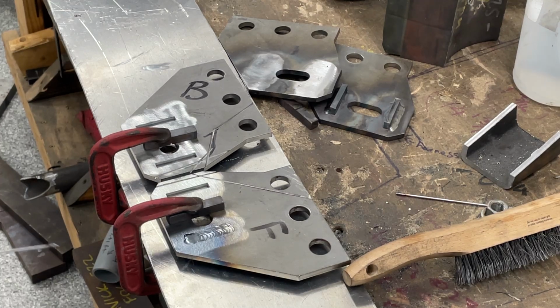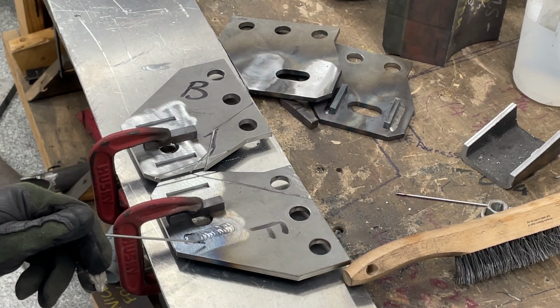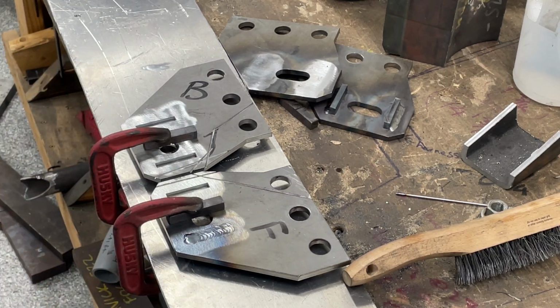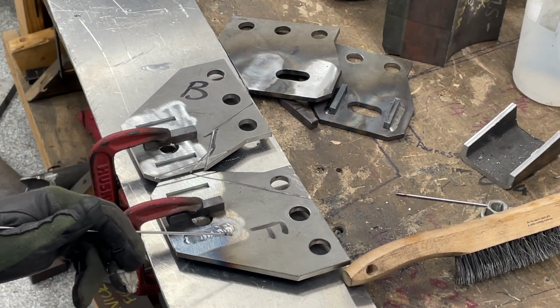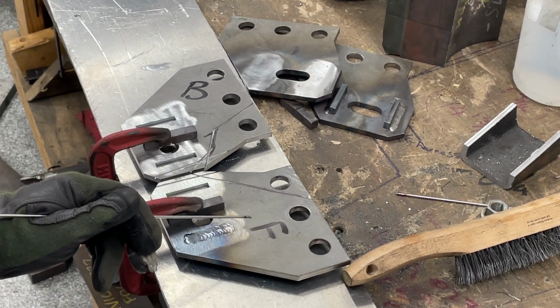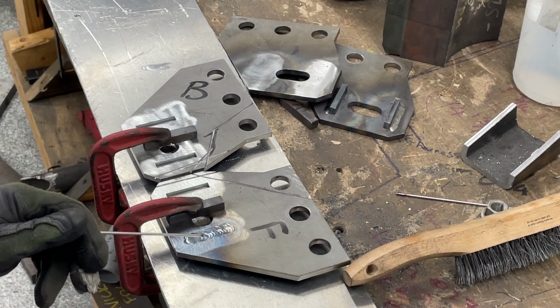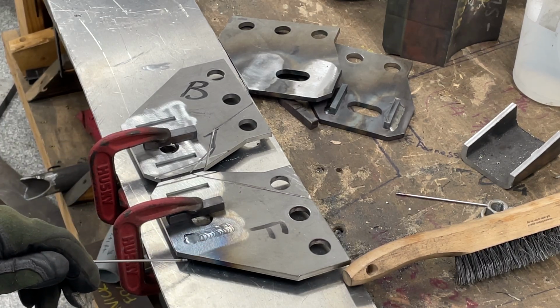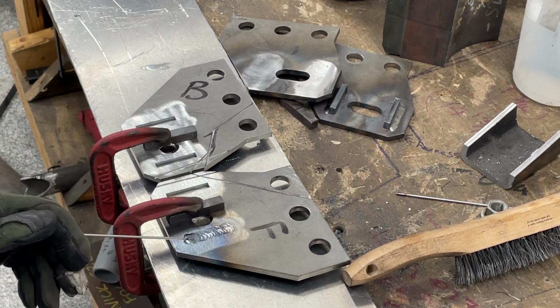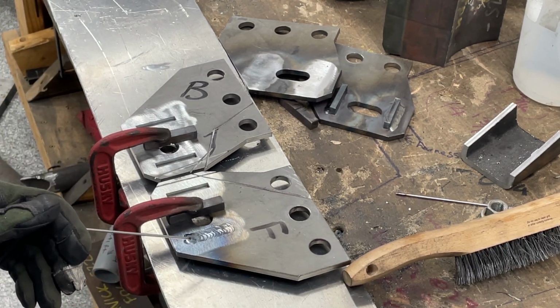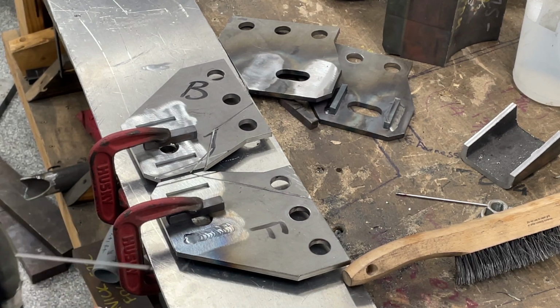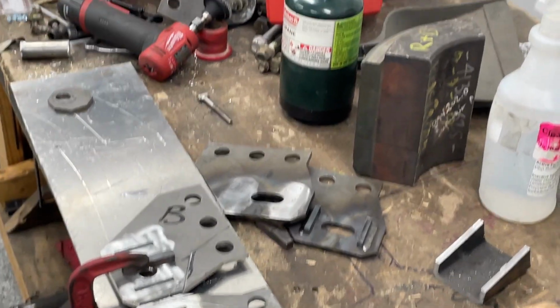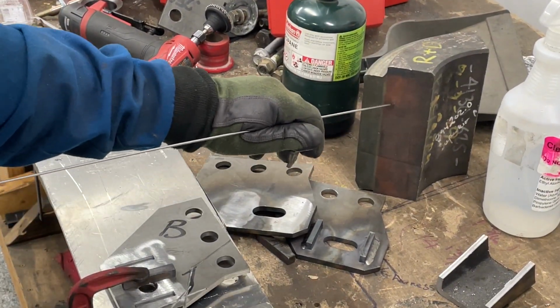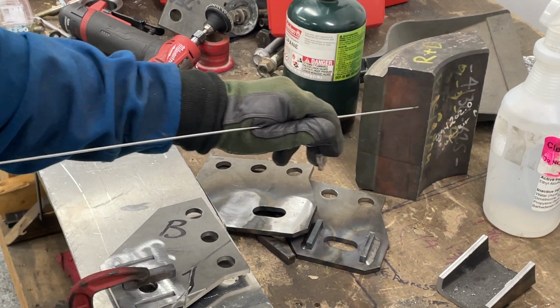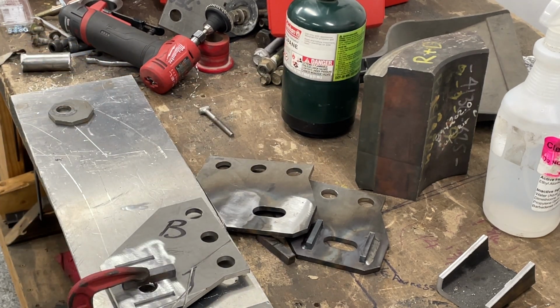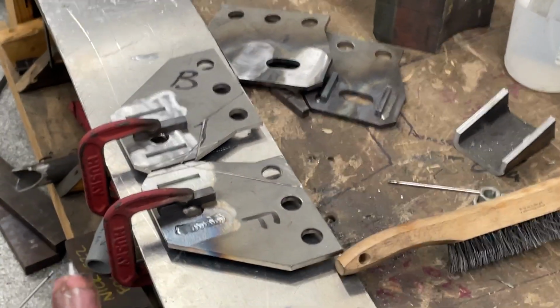And you can see that the heat is more focused on where I'm stopping up here, but this blue hue is going to keep growing that way as time goes on. In the world of knife making, you can actually use this color to determine the actual temperature of the part. Like this is room temp, this is 400, and then this is up to 500, 600, and 700 plus. But when it comes to materials that are 1/4 inch thick and thicker, you really need a temp stick to get accurate readings, or a temperature probe like a thermocouple. This is merely a surface condition, not through the thickness of your material. And that's actually the reason why other industries stopped using materials like 4130, because their through hardenability wasn't as consistent as some of the more modern alloys. Because the area outside would be at a certain temp and the stuff inside would not.